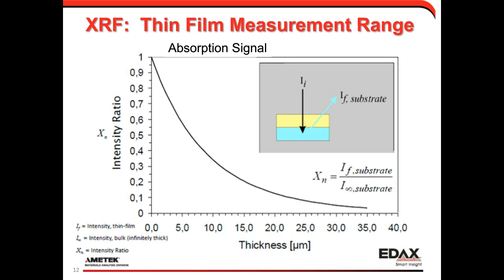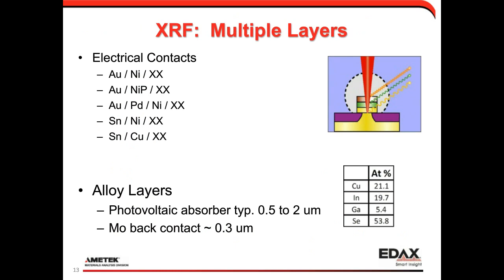You can also measure multiple layer stacks, and I show some examples of that. You can also measure the composition of the layers as well. So for example, in the electrical contacts market area, they use nickel coatings for certain applications and nickel phosphorus coatings for other types of applications. You can measure, for example, the composition of the nickel phosphorus layer.